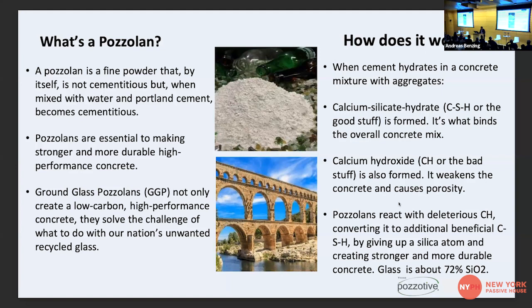What happens is, because ground glass pozzolan is an amorphous silica, the silica atoms are loosely bound, they're not tightly bound like a crystalline silica. And during that calcium hydrate reaction, the silica atoms split off and bond with the free calcium hydroxide to create more calcium silicate hydrate, or more bonding agent that bonds the aggregates together. So it makes a more durable, stronger, more resilient concrete. And as do many pozzolans.